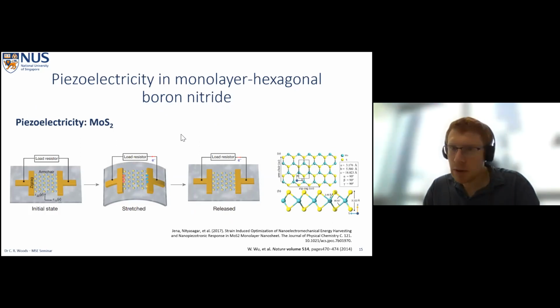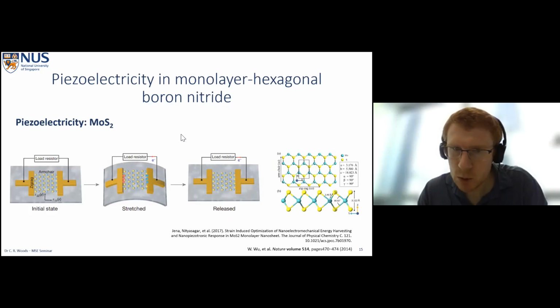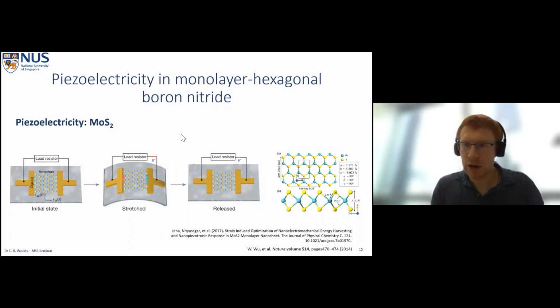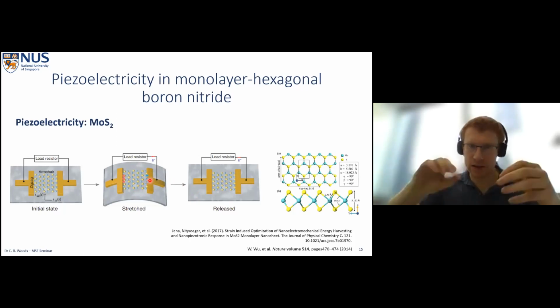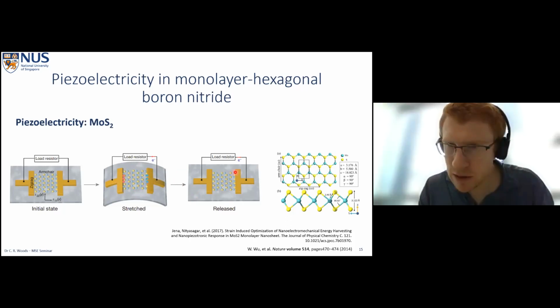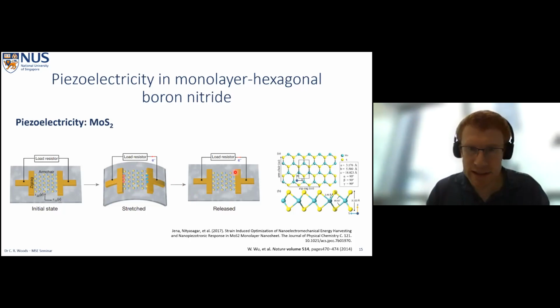So the question is about MoS2, and when we bend the polymer substrate, what's the role of rippling or curvature on the result here? Well, the bending here, the curvature, is the introduction of positive expansive strain. So that's what's introducing the strain here. And because we have a piezoelectric material, when you increase the curvature, that's what causes our potential difference from one side to the other, and they use that to drive the electrons in a circuit. You can think of this curvature as being like, what's the shortest distance between two points? What's the shortest distance between my two contacts?